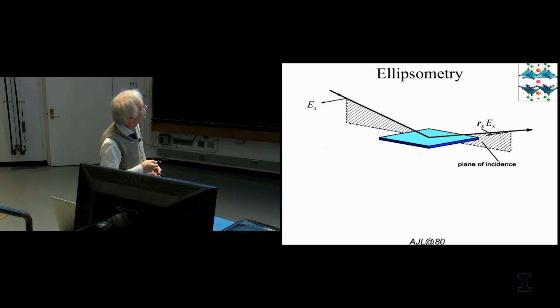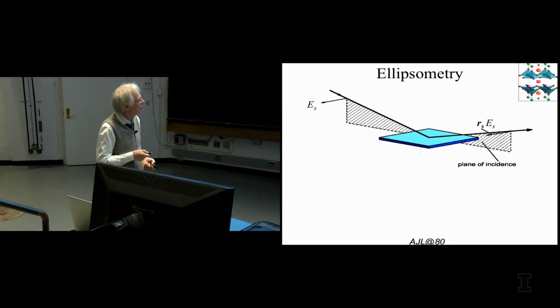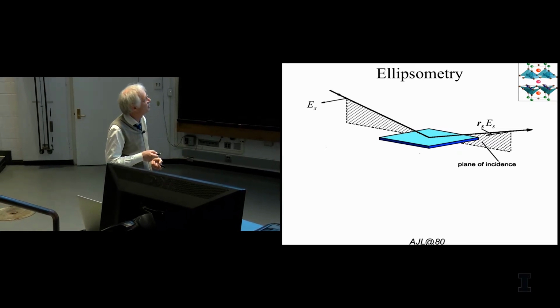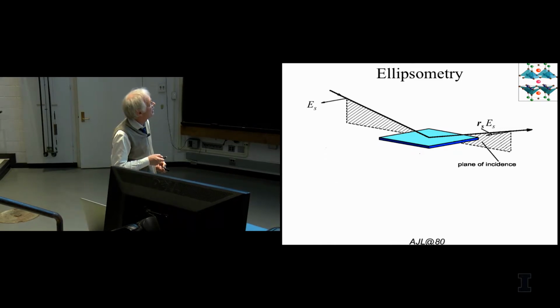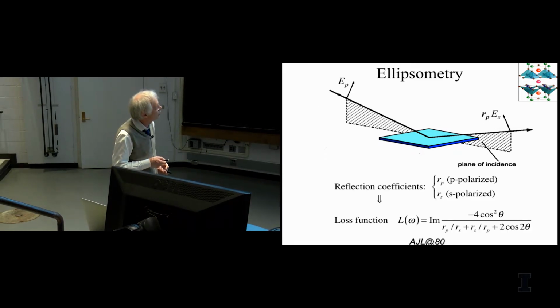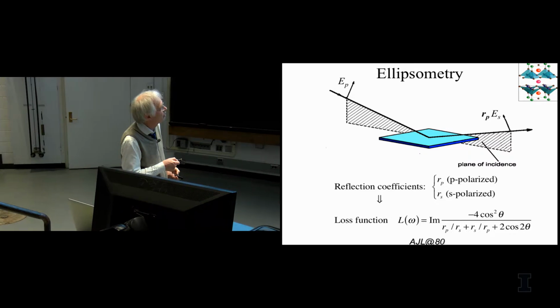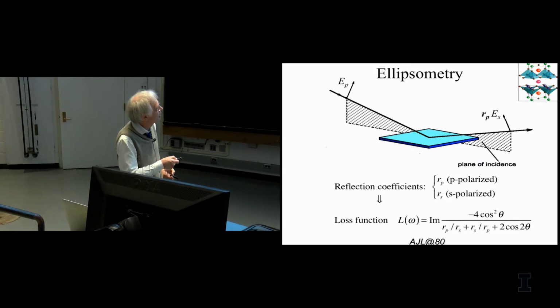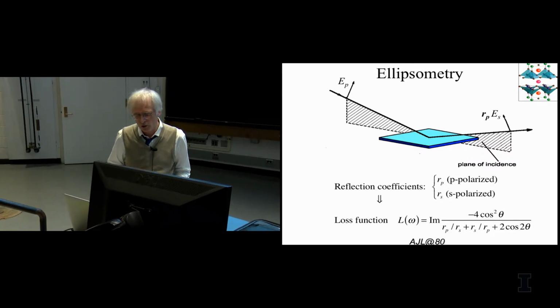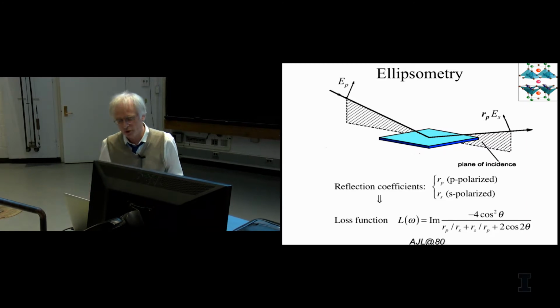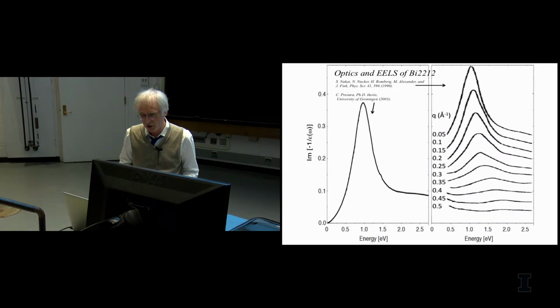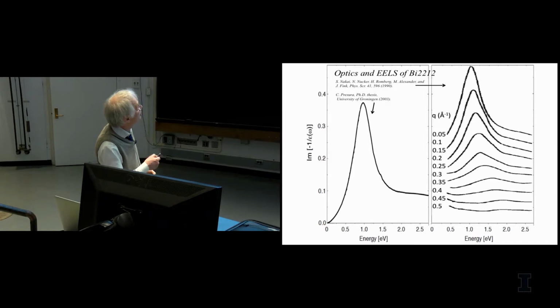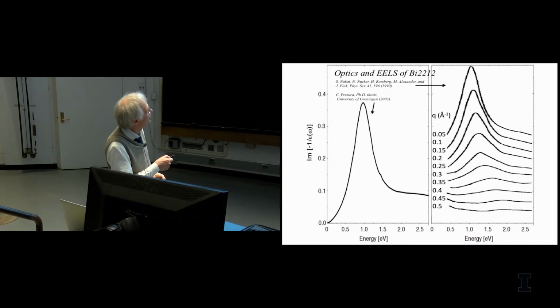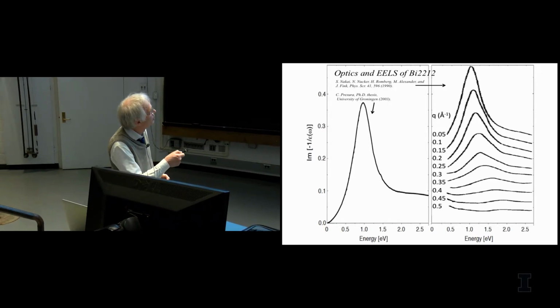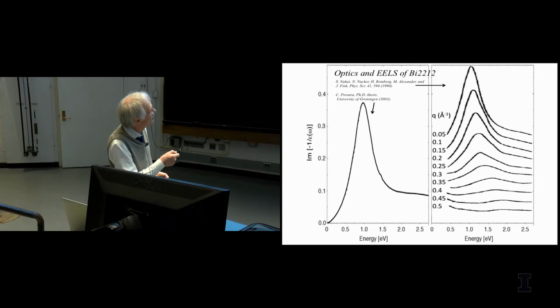And so how do you do ellipsometry? You measure the reflectance of a ray of light on a surface using two kinds of polarization, S and P. You take the ratio of the two coefficients, which gives you Rp over Rs or Rs over Rp. You put it in this formula and it gives you the loss function. There's a whole lot more to it having to do with correction for the c-axis and all that, but this is the basis of it. And if you do that, this is the loss function after correction for the c-axis. This is what you get if you do energy loss spectroscopy in transmission.